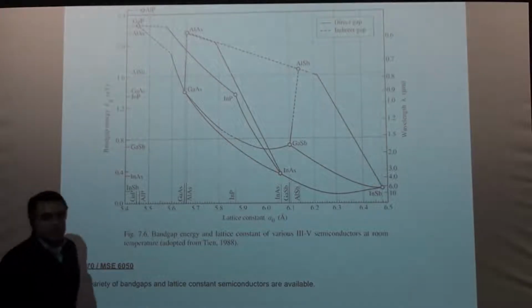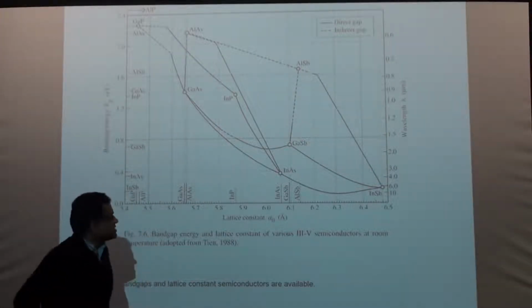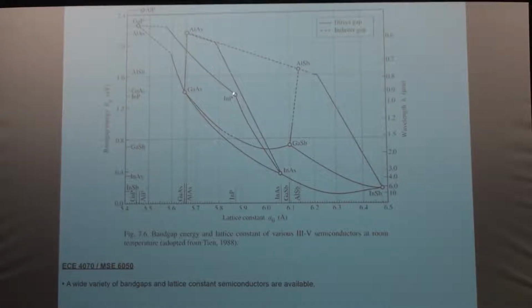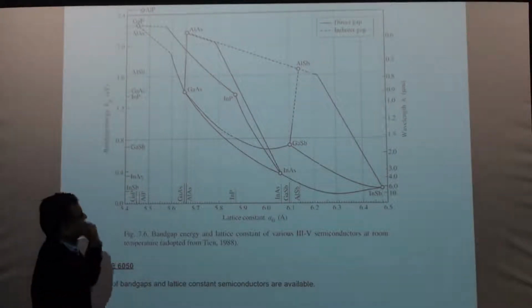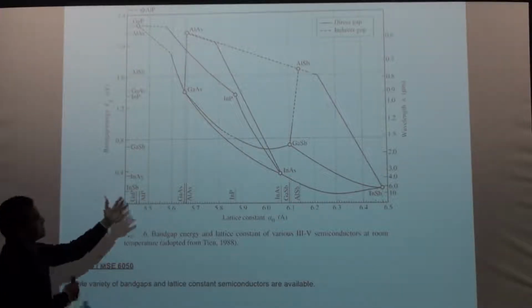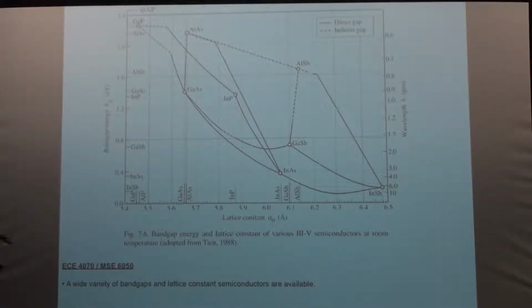Yeah. Is that commensurate or is that fully relaxed? This is completely crystalline and completely commensurate. And you can grow, for example, half a micron of this on top of this, and it will be a perfect crystal. On the average it will be indium gallium arsenide. There will be no dislocations, there will be no strain. You can grow very, very thick that way. And this is one of the very powerful tools in semiconductor heterostructure physics, that you can mix two bandgap semiconductors, and you can now start designing a lot of things that I'll talk about.